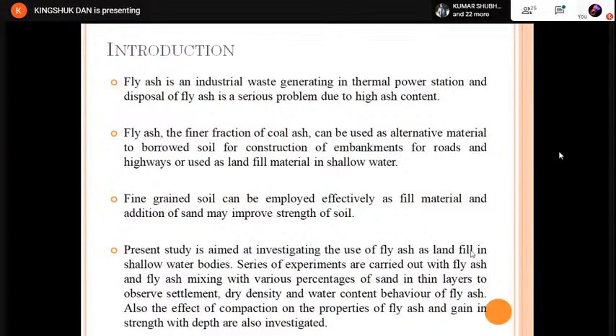And as we know, fly ash is clay-silt type in nature, so it can be similar to fine grained soil, which can be employed effectively as fill material. And if adequate sand is mixed with it, then its strength can be enhanced. Now, in this study, it is attempted to investigate the use of fly ash as landfill material under shallow water, and a series of experiments are carried out to investigate the settlement, dry density, and water content behavior of fly ash and fly ash mixed with sand layers, and also the effect of compaction and compacting effort on the characteristics of the fly ash, and the strength characteristics are also investigated.